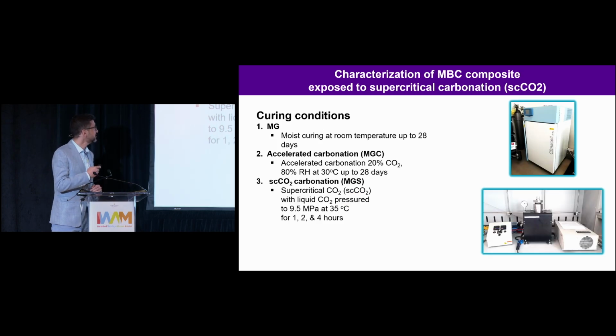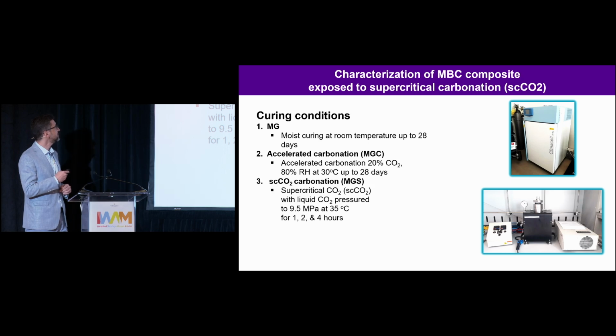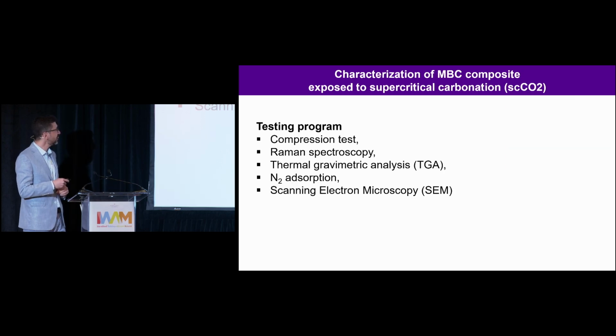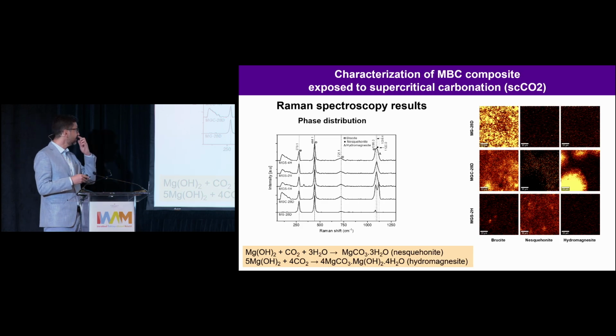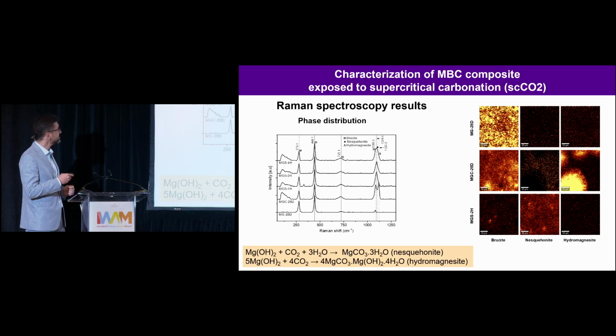So we have 3 samples. One is the magnesium cement cured in the air, the other one is in the accelerated carbonation chamber that I mentioned, and the third one is the supercritical CO2, and we compare the results. There's a comprehensive testing program that I'm not going to show all of, but the most important one, the Raman spectroscopy, shows us the main phase, as mentioned, is brucite, but we are able to see the peaks for nesquehonite and hydromagnesite. The one that we are seeing here is hydromagnesite at 28 days of curing in accelerated carbonation condition. But if we use supercritical CO2, the hydromagnesite peak disappeared, and mostly we have the nesquehonite phase.